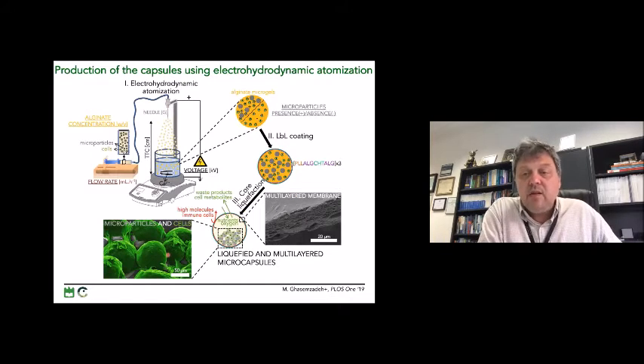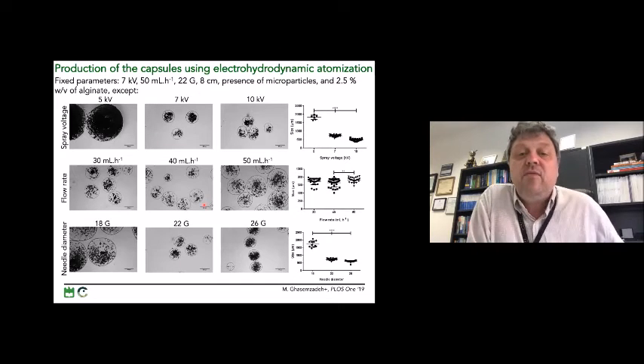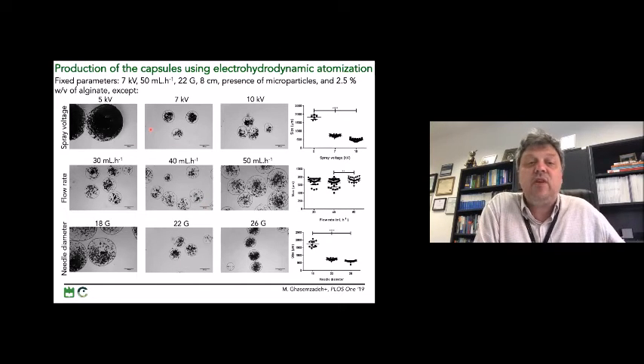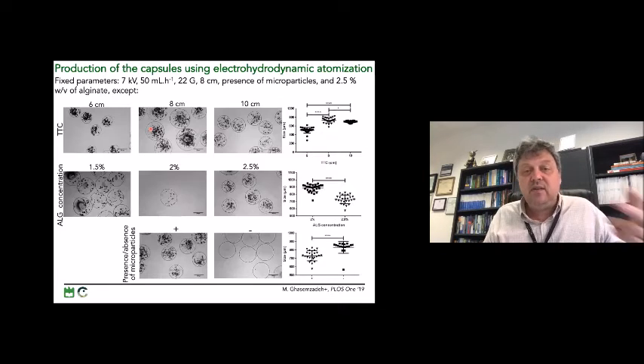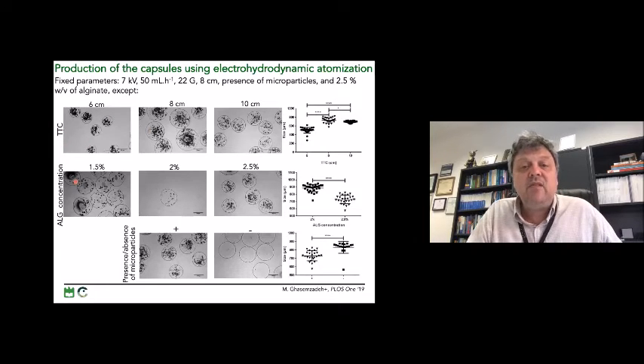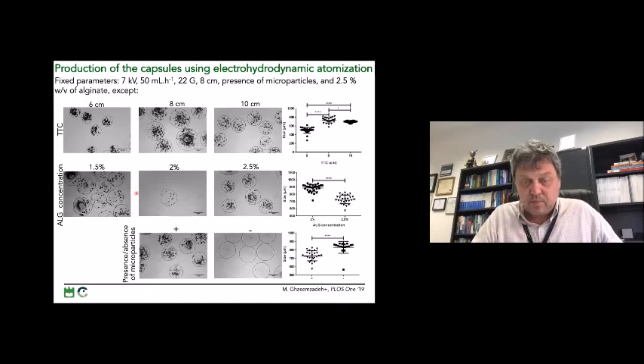So if the ingredients inside the capsules are very well defined from the very beginning, we anticipate the formation of a microtissue in a very autonomous way. So we can vary several processing parameters, such as the spray voltage, the flow rate, the diameter of the needle, the distance to the collector, or the alginate concentration. And so in this case, we can control the size of the capsules between, I would say, 200 micrometers up to 1 or more millimeters.